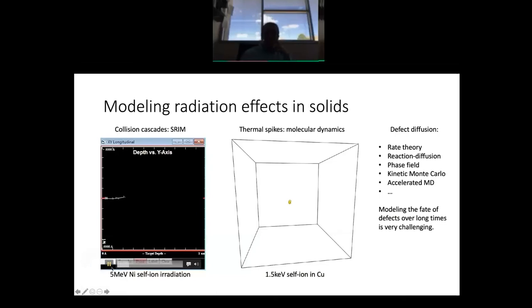Okay, so SRIM is a program that basically just models binary collisions, right? So it doesn't take into account these nonlinear interactions between many bodies, more than two bodies. It just thinks of the particle interacting with isolated atoms in the solid, and that turns out to be a perfectly good approximation for studying collision cascades. So this process of the particle bouncing around and losing energy to electronic stopping and creating primary knock-on atoms, all these things are reasonably well studied by this binary collision approximation in SRIM.